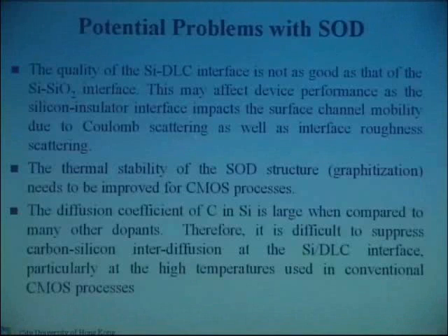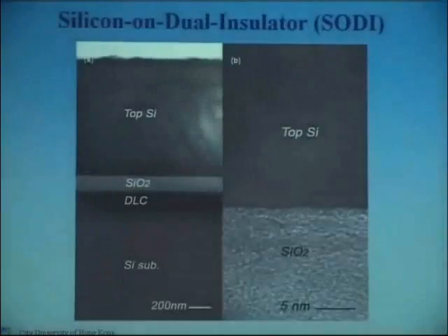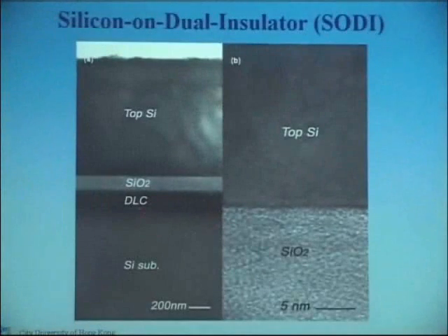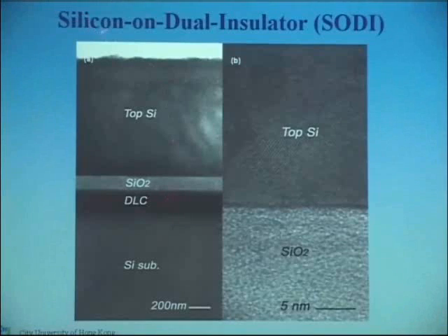These are the problems. One is the quality of the interface is not very good. The thermal stability is not very good. And also there's diffusion across the boundary between carbon and silicon. So we went ahead and did, why not make some combined technology with SiO2. So we have what we call dual insulator, meaning that we have both the diamond and the SiO2.